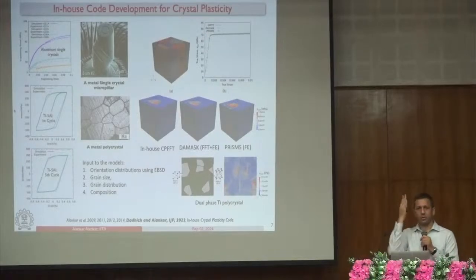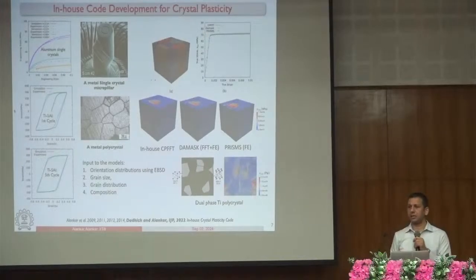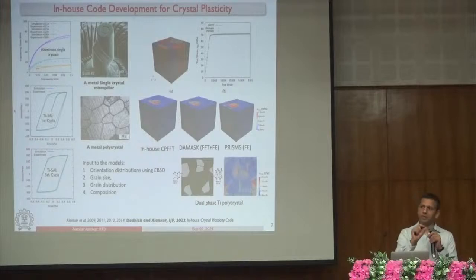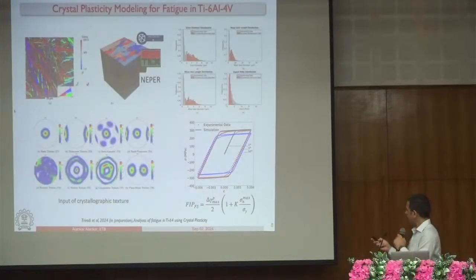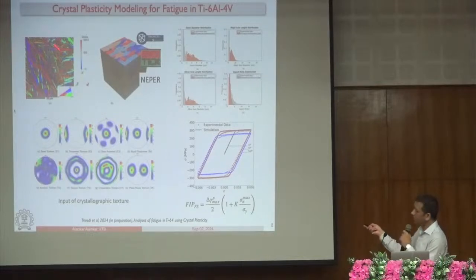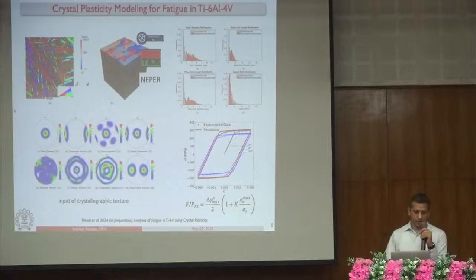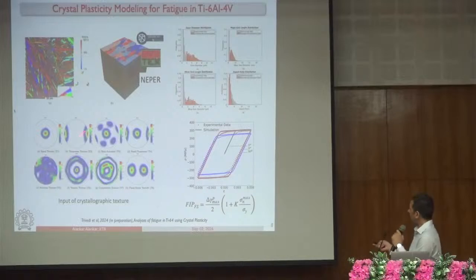By using such simulations, you can do cross section and can see what is happening inside the grain, what is giving rise to the deformation that you are seeing on the surface, right? This is an example of a fatigue simulation where the picture on the top left is an orientation image of Ti64, which is titanium 6 aluminum 4 vanadium, the alloy about which I was mentioning earlier. And this is the lamellar structure, which is typical of quickly cooled Ti6 aluminum 4 vanadium.